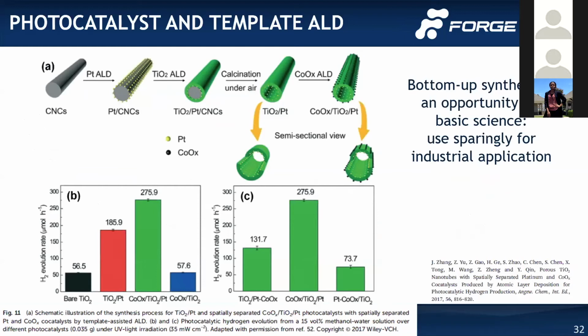I mentioned on that ALD treasure map for catalysis, photocatalysis - this is a bottom-up synthesis. I'm taking a carbon nanotube and doing complete ALD processing: deposition of platinum, titanium dioxide, then removing the carbon nanotube and depositing cobalt oxide, all in ALD steps, then looking at hydrogen evolution. You can get really interesting, great results with ALD with every step being ALD in a bottom-up synthesis, but that may not be economically viable - and that's something we look at at Forge Nano.